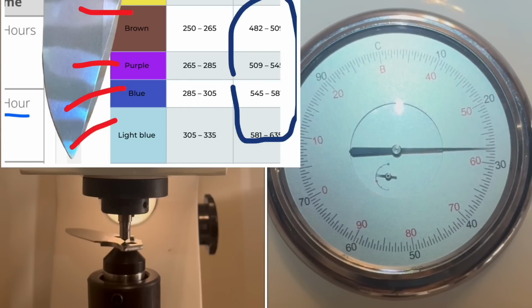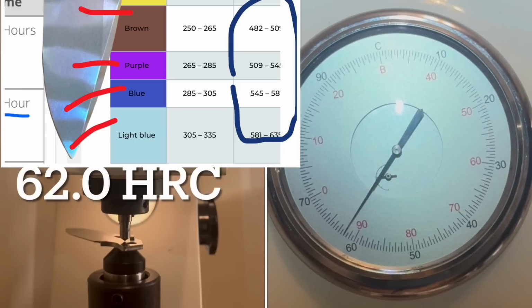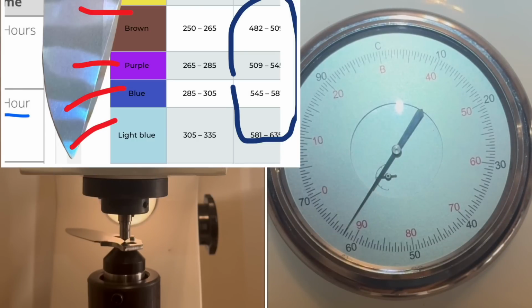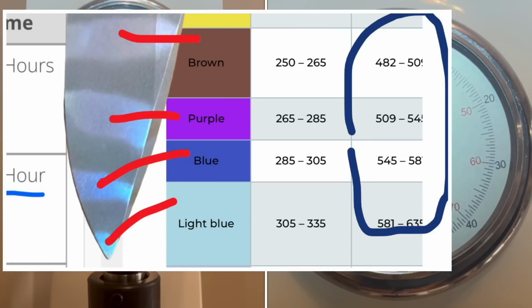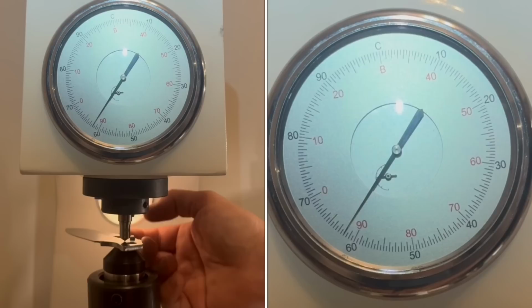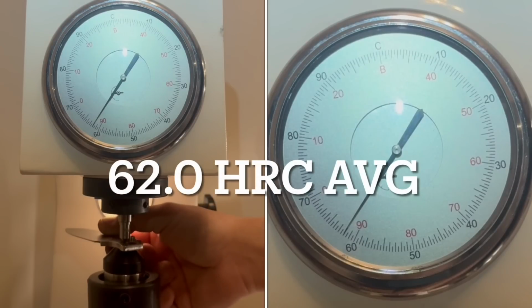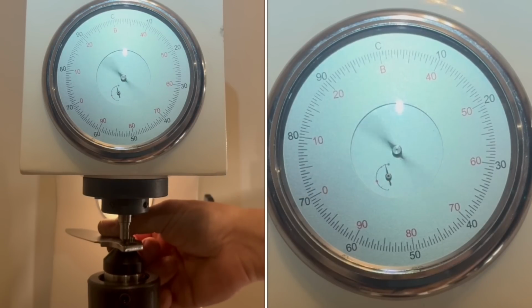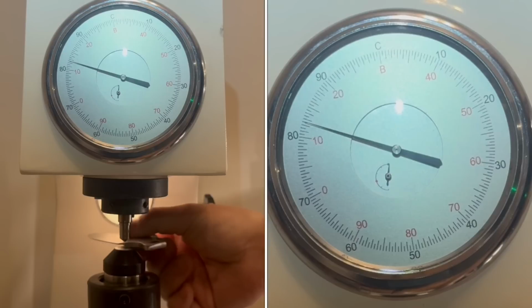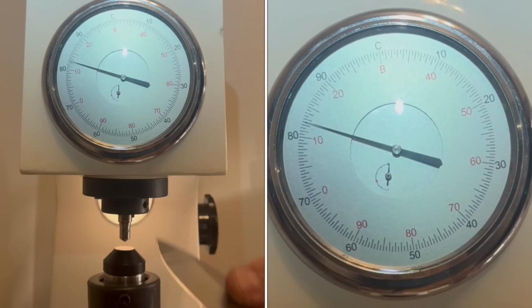And this blows my mind. Apparently, to get these colors of the rainbow, especially browns and blues, they heated this blade to over 500 Fahrenheit. Every MagnaCut heat treat procedure I found online specifically doesn't recommend exceeding 500 Fahrenheit. We can say with certainty this process took place before Cerakote, and therefore I would conclude that Cerakote itself did not affect the hardness. But what about the performance?